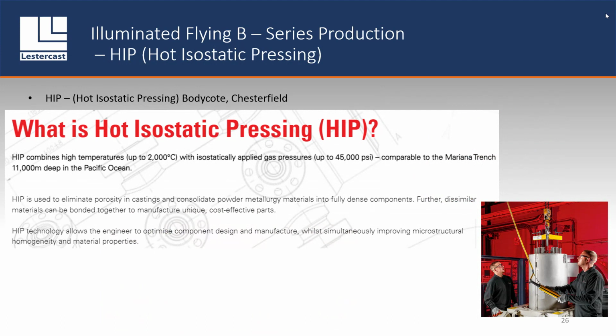The HIP process is a high temperature under extreme high pressure, and it will push away any small micropores within the material structure. If you get the opportunity to go to Bodycote at Chesterfield, it's quite amazing. Some example parts with large cavities inside the component, and after the process, those cavities are filled. Of course, that material moves from somewhere else. So we were always mindful that if we were going through the HIP process, what it would actually do to the geometry of the part. Thankfully, we get no distortion or movement during that process, and it's not given us any issues on dimensional.